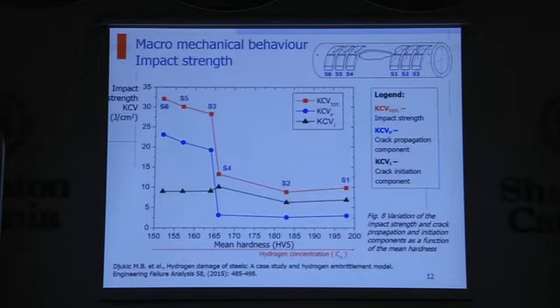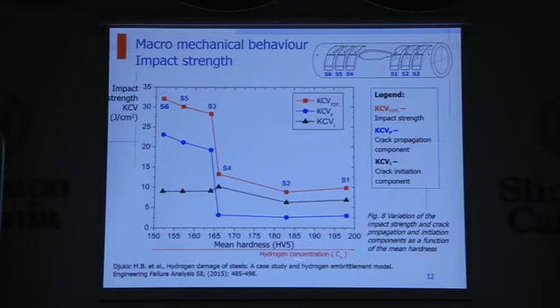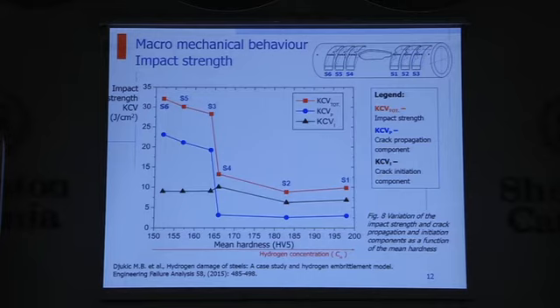Results and discussion: here is the variation of the impact strength, crack propagation, and initiation components as a function of hydrogen content in Charpy V-notch specimens, shown in the picture below. As we can see, we have a sharp transition from ductile to brittle fracture, which corresponds to the critical hydrogen concentration, and we have a very large drop in impact strength. The blue curve is the crack propagation component; using instrumented impact testing, we can calculate the crack initiation and crack propagation components. This happens in the case of S3 and S4 specimens.